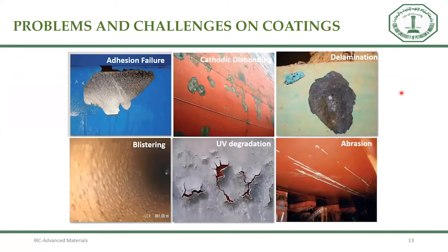Even though we are using multi-coat systems, there are plenty of parameters that can easily influence the performance of the coating and result in failures. These are the important failures in epoxy coatings: adhesion failures due to inadequate surface preparation, cathodic disbondment because of the high overvoltage passed through the coatings, since we are always using coatings along with cathodic protection systems, and delamination, blistering, UV degradation, abrasion. These are the important problems faced by epoxy coatings in the real-time environment.